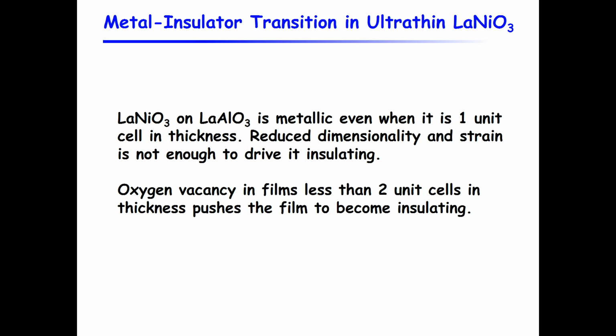Although you could, the reduced dimensionality and strain can make it more insulating, but it's still metallic until you have oxygen vacancies, which become more dominant around the interface. And that finally drives it to be insulating. Why we see these higher oxygen vacancies at the interface, we don't have evidence to show one way or the other. But we do show that when you approach this interface, you see more and more oxygen vacancies, which turns out to be important for this metal insulator transition.